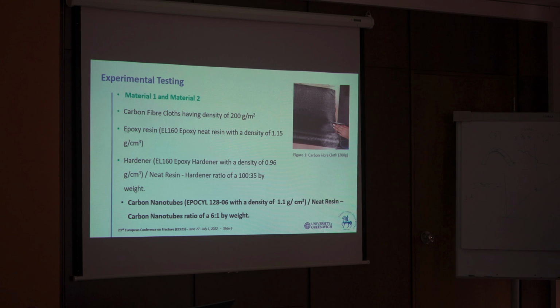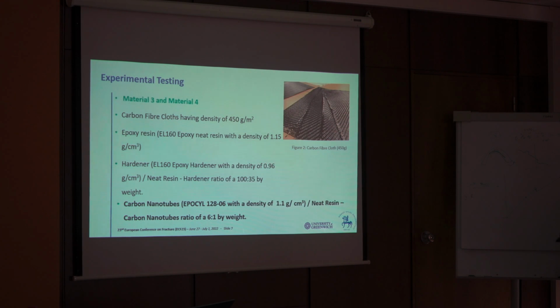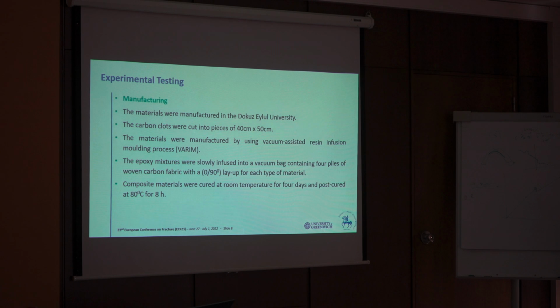For the ones with the additive, we used the carbon nanotubes, as I said before, the EPOCYL 128-06 with a density of 1.1 gram per cubic centimeter, and it was mixed with the neat resin, which is this one again, by the ratio of 6 to 1 by weight. So the only difference between materials 1 and 2 and materials 3 and 4 is the densities of the carbon fiber cloths.